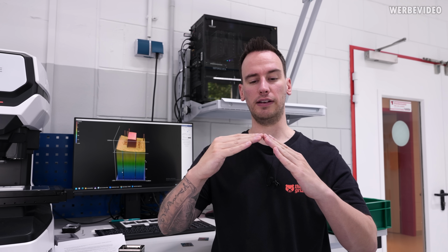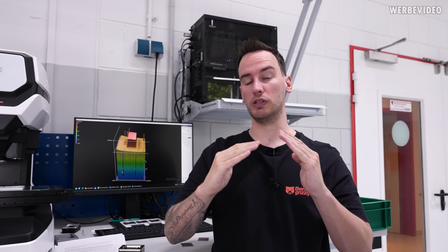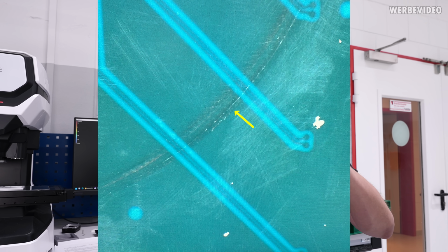But even if you add a 45-degree angle, there is still this defined edge. And this defined edge was pressing into the PCB, and if you mounted it with enough contact pressure and mounted it multiple times, then this was causing the damage to the CPU. It was just pressing into the PCB. Then we inspected this underneath a microscope, and we could see a cut in the PCB, probably damaged some kind of traces on the PCB and then damaged our 3 CPUs.